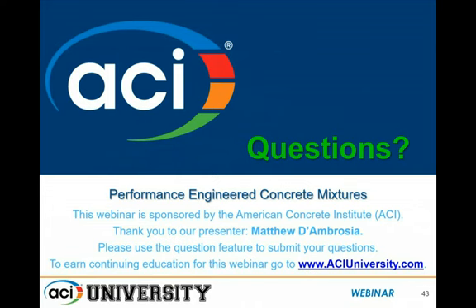There are admixtures out in the industry today. The hydration stabilizers would be the class of materials that I would encourage you to investigate. These hydration stabilizers can increase that time frame even further. And then there are slump retention products as well. And the slump retention products, in conjunction with hydration stabilizers, can give you mixtures that have better time frame for placement than you may have.